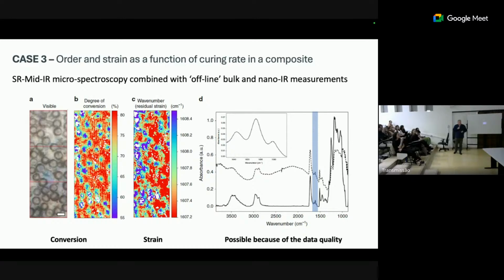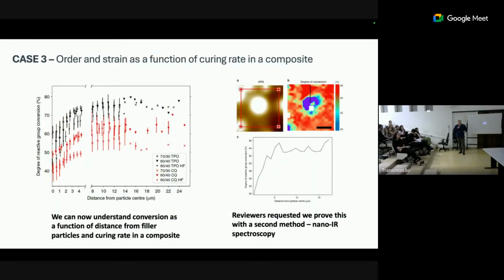And so this is what we managed to produce. We managed to look at a composite at a single particle level. We managed to map degree of conversion with respect to the particle centers. And because we've got such high quality spectral data, it also allows us to look at very subtle shifts in that data in order to pull out something we call molecular strain. So we can now understand that, again, if you ramp up your polymerization rate, how well you're going to convert at an interparticulate level, but also how much strain you generate in the system. Again, on the left, I'm not going to go into huge details of what we're showing here, but effectively you have a boundary layer around the particles that has lower conversion and lower strain, but it is set by the composition and how quickly you set the polymer.